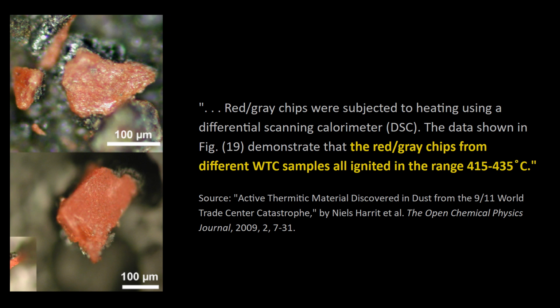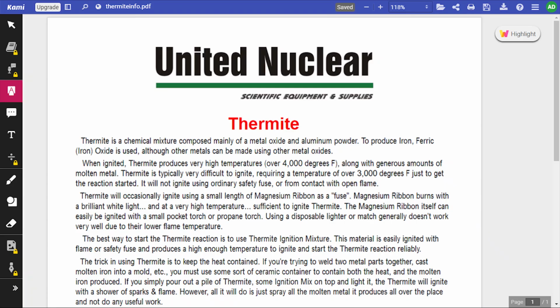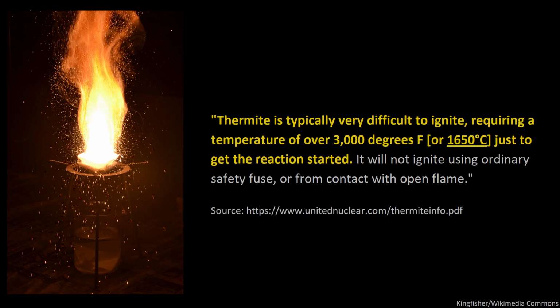First, there's a glaring issue with the ignition of these chips in the DSC. Quote, "The red-gray chips from different World Trade Center samples all ignited in the range 415 to 435 C," end quote. Without realizing it, they appear to have just resoundingly and conclusively disproven their own hypothesis. In a publication on thermite, United Nuclear writes the following, quote, "Thermite is typically very difficult to ignite, requiring a temperature of over 3,000 degrees Fahrenheit or 1650 C just to get the reaction started. It will not ignite using ordinary safety fuse or from contact with open flame," end quote.